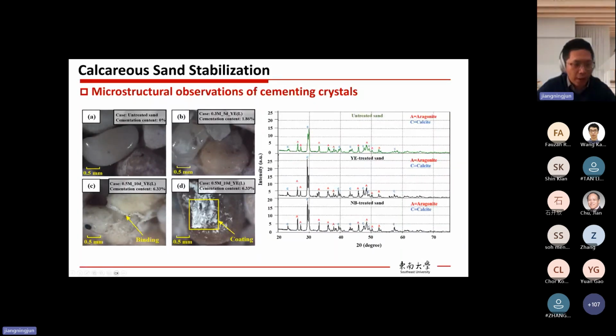In addition to the interparticle connections, we could also see some formed crystals coating the surface of sand particles. Then through the XRD analysis, we could see that after MICP treatment, we have more calcite. For example, this peak and this peak are new peaks compared with the original soil. This also demonstrates the formation of new calcite precipitation from MICP.